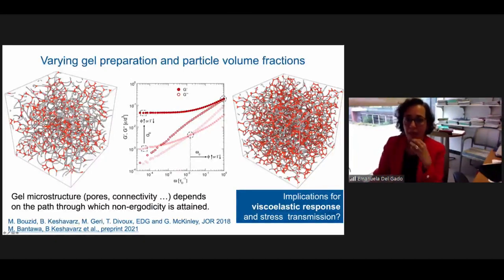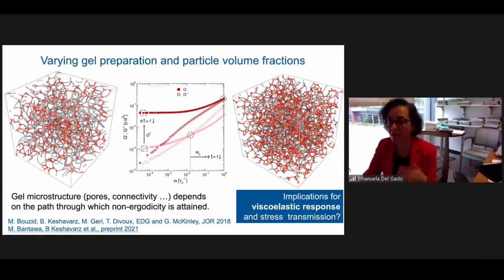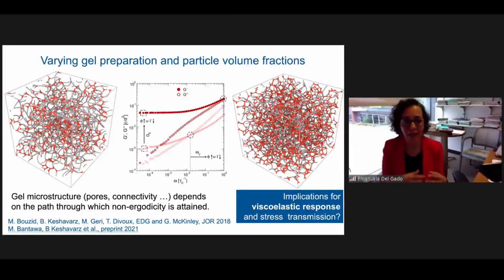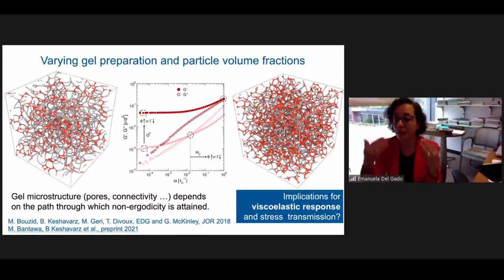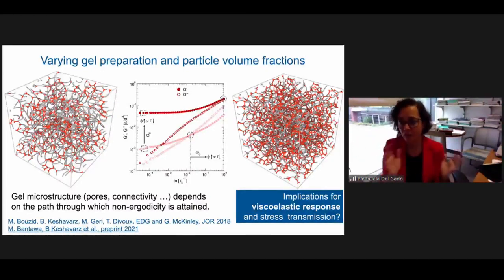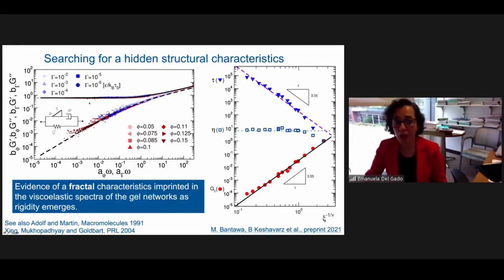And by doing this, we can obtain a wide variety of structures, even with the same volume fraction, and a wide variety of structures by changing the volume fraction. So if you change the structure, going from the left to the right, you change not only the modulus, but the whole viscoelastic spectrum. And so, I'm back to the figure that I was showing in the very beginning. I have a lot of different structures, a lot of different viscoelastic spectra. So what? Well, what we realize is that you can reconnect all of these gels into a unique viscoelastic behavior by building this type of master curve where all our gels end up being able to go.